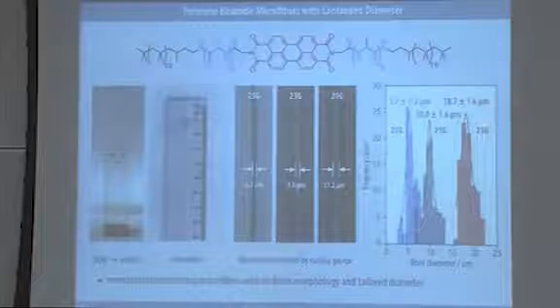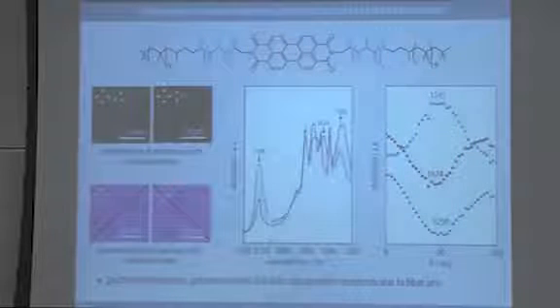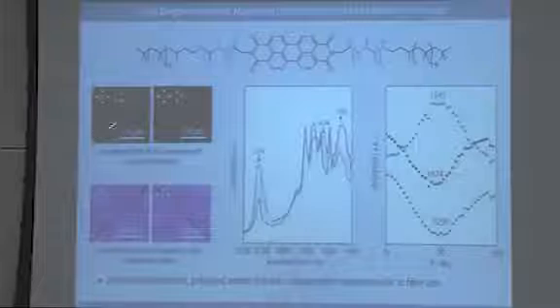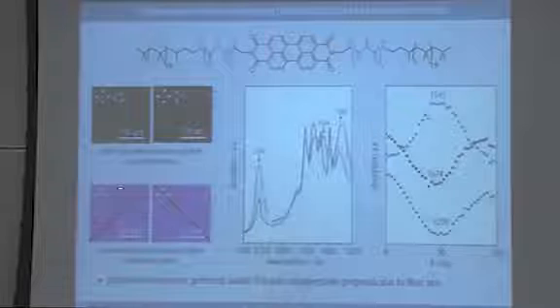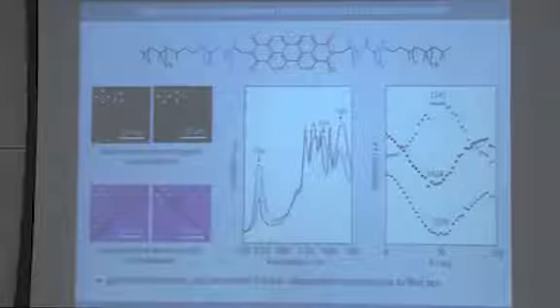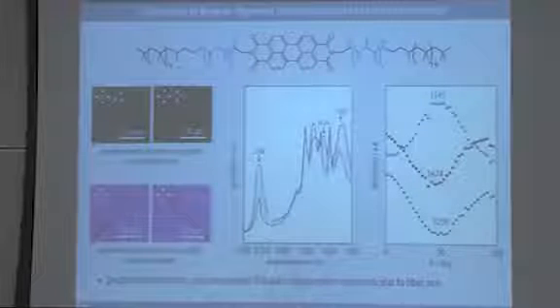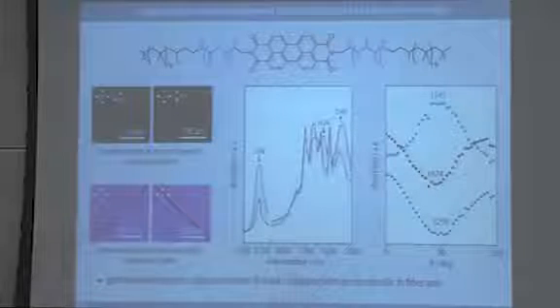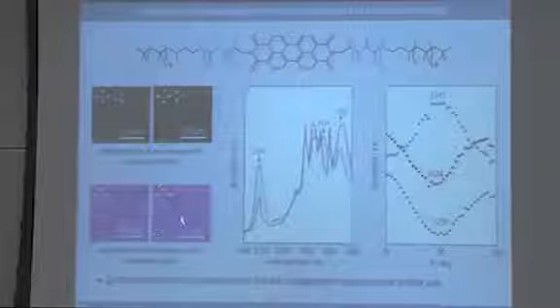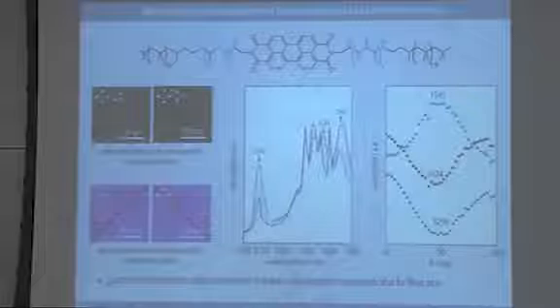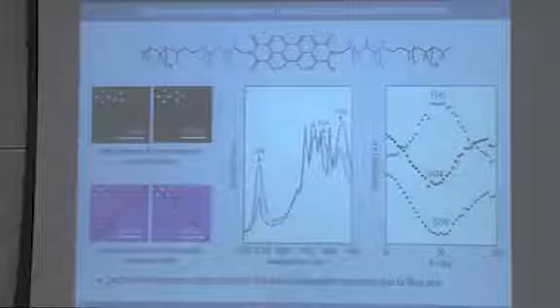And these were highly aligned, internally highly aligned species, as you can see from polarized optical microscopy in diagonal position or in extinction position. Using a retardation plate told us that the fast refraction direction is in fiber direction, which by analogy to the literature tells you that the oligopeptide segments, so the side groups, are actually lining up vertical to the fiber direction.